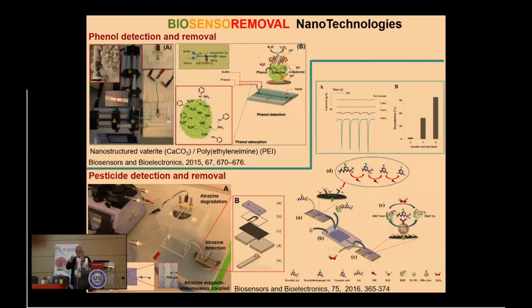So we try to combine together sensing of contaminants with destruction, and this is a project we collaborated on with Tokyo, with a very well-known group working with boron-doped diamond electrode. You know, the electrodes may be of different material, and boron-doped diamond electrode has a very broad potential window, which is very good because you can do nice detection, but also you can apply high potential to destroy, for example, contaminants. And you see here, as an example, in the electrodes we are doing some detection of some pesticides, and at the same time destroying them by applying high voltage. So we have a kind of system where you see here the signals coming from the pesticides, and after destruction, we have almost nothing in the sample.